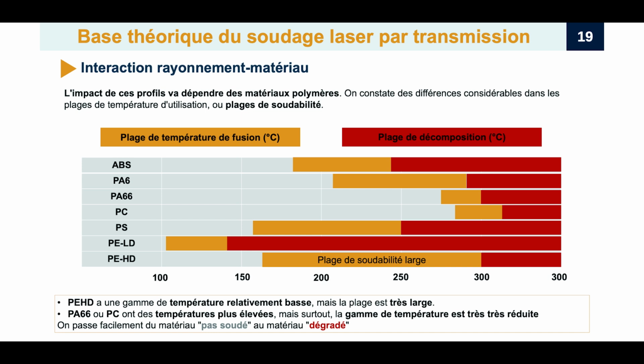Narrow windows. How narrow are we talking? For something like polycarbonate, the gap between the temperature where you get good chain diffusion, just above T-flow, and the temperature where it starts to noticeably yellow, bubble, and degrade, T-deg, might only be maybe 10 or 15 degrees Celsius, sometimes even less. Wow, only a few degrees between perfect weld and burnt plastic. It's incredibly tight. Welding polycarbonate or similar narrow window materials isn't just manufacturing. It feels more like microsurgery. Any tiny fluctuation, a blip in the laser power, a slight change in scanning speed, maybe an inconsistency in the material itself can instantly push you from the sweet spot right into the degradation zone. And ruin the whole part, which could be very expensive.